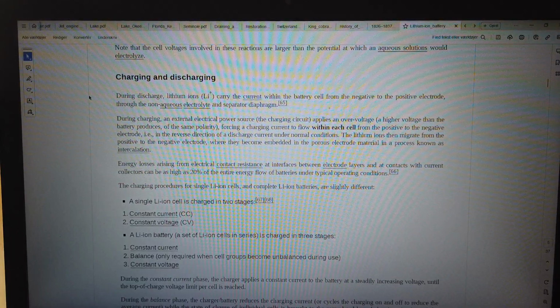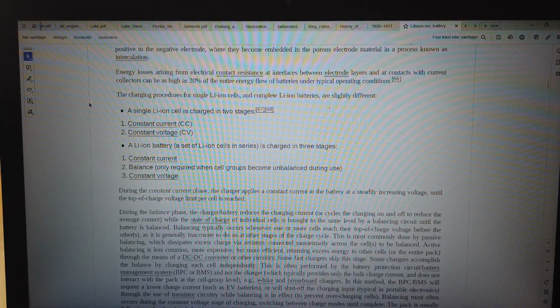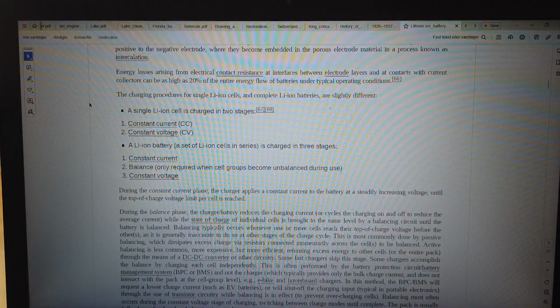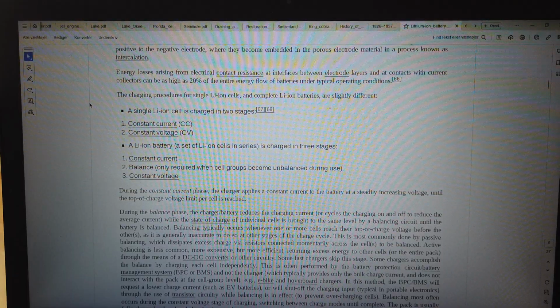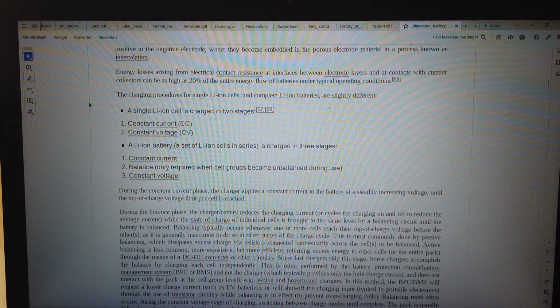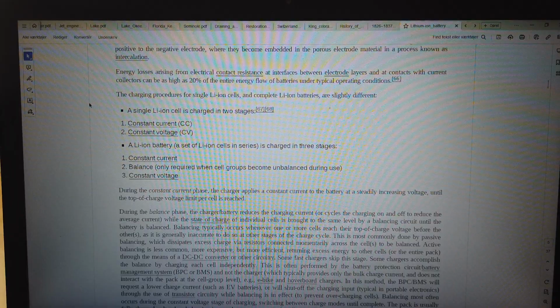Energy losses arising from electrical contact resistance at interfaces between electrode layers and at contacts with current collectors can be as high as 20% of the entire energy flow of batteries under typical operating conditions. The charging procedures for single Li-ion cells and complete Li-ion batteries are slightly different. A single Li-ion cell is charged in two stages.